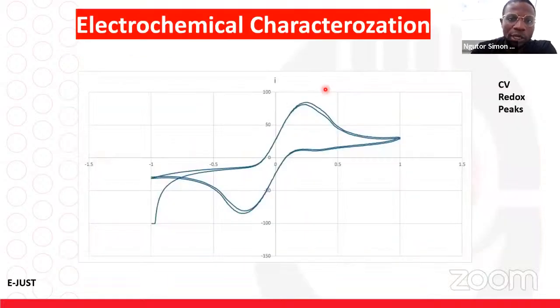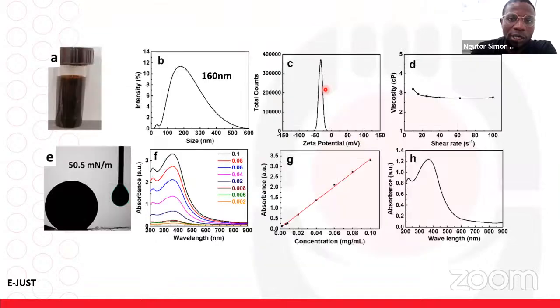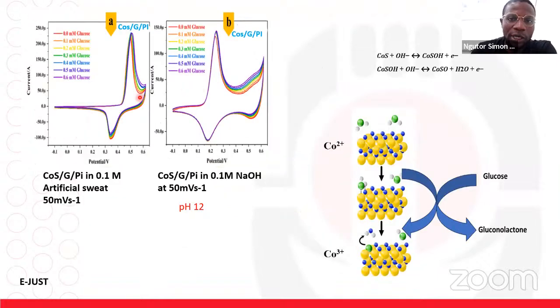So electrochemical characterization, like I showed before, this is the CV performed, and this is cobalt sulfide on graphene and polyimide. This is an artificial sweat. This is in NaOH at 50 millivolt, applying a reverse bias potential to balance the pH. You could see the pH at which this senses is just 12, more like a high pH.